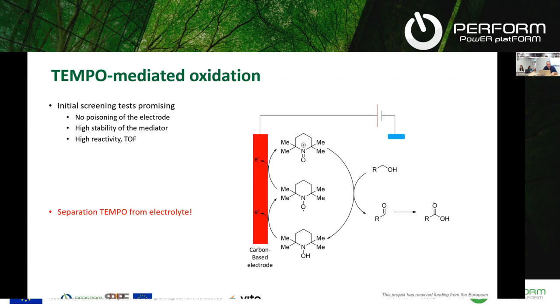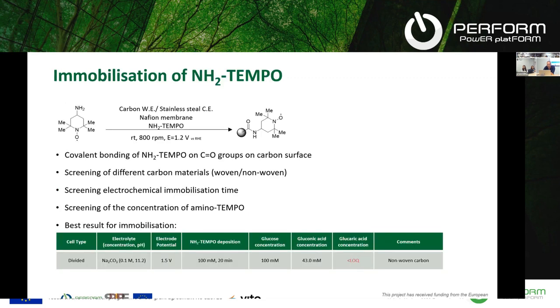Of course, mediated electrolysis always implies an issue of separation, and also in this case, the tempo is an organic mediator or catalyst, which is difficult, of course, to separate from the electrolyte as it fully solubilizes and needs to be taken care of. One of the first things that we tried to investigate was to actually immobilize the tempo onto the electrode surface, and therefore we used a specific form of tempo, which was amino tempo. So you have the amino group.